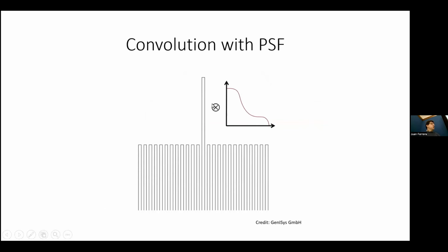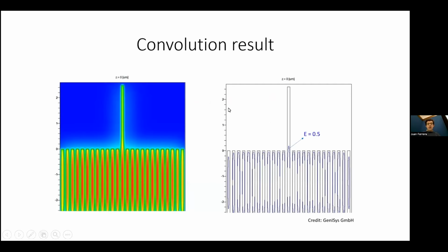And now I'm going to show you how the proximity effect correction is done. So let's say that you have this pattern, you want to expose a grating with a long line in the center. And then you're going to, again, convolve with the point spread function to see how the energy is deposited. You can see that there's very little energy being deposited here and on the edges,